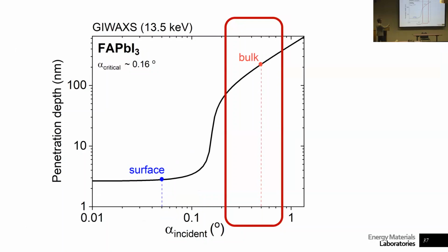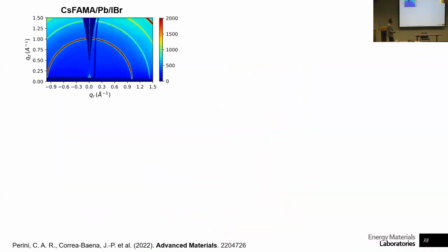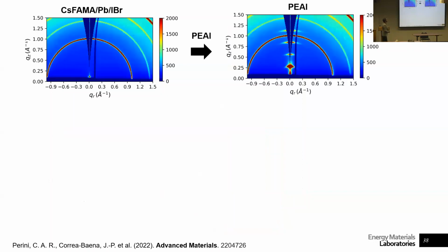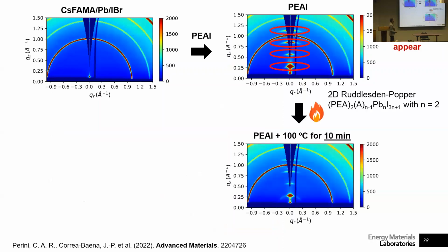At 1 degree, we look at the bulk, and at 0.1 or below, we look at the surface. So that's a penetration depth of about 2 nanometers versus 200 nanometers. So two orders of magnitude of difference in terms of the depth profiling that we can do. That gives us information like this, where we can basically differentiate between the bulk and the surface, and what kind of structures we have in there. For example, how materials degrade over time.